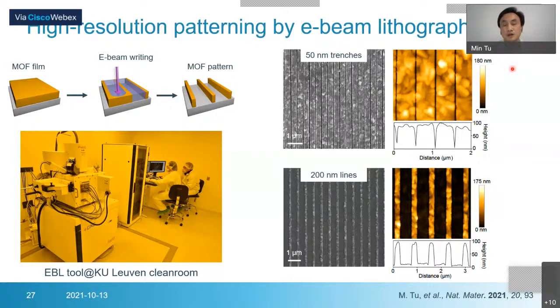But with the mechanics study, it has this electron-induced change. So we can also use this patterning by electron beam lithography. It's kind of the same. You have the MOF film, but here we don't use any mask. We have an electron beam to write on the surface. Then after irradiation, we immerse this sample into DMSO to remove the exposed area, and then we have the MOF pattern.